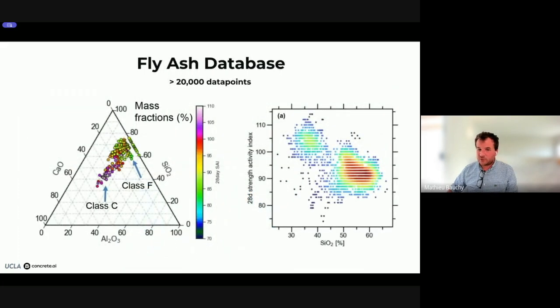And then we need to also have this for any other kind of material that we use to replace cement with. So for example, fly ash is typically the main material that cement is replaced with. So we have the same types of information here, where we have accumulated about 20,000 different data points for fly ash of different compositions.